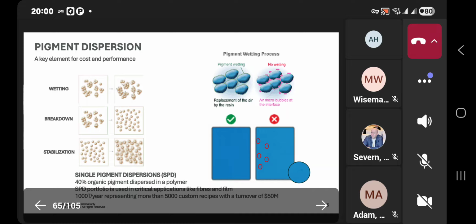On the left side of the picture, we see a deep and intense blue surface with no pigment agglomerates. In the end, the dispersion is about avoiding those agglomerates in customer end products. This is a key factor for processing and quality performance, which can easily drive cost up. And this is particularly important for us because of our SPD portfolio, for which we produce more than 1,000 tons a year that end up in more than 5,000 custom formulations representing 50 million turnover. Next slide, please.